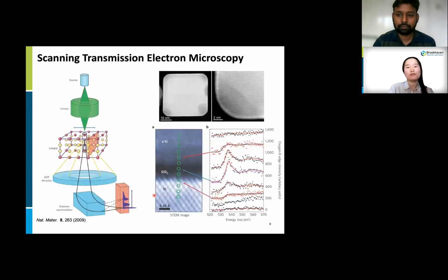In general, we use a parallel electron beam in TEM, but we can also make a small electron probe, and we can scan the sample with the probe electron beam. In this case, we refer to the technique as scanning transmission electron microscopy, which is STEM. General TEM instruments offer both STEM and TEM operations. The beauty of STEM is we can do chemical analysis at atomic resolution. Here is an example of silicon oxide and amorphous silicon layers.